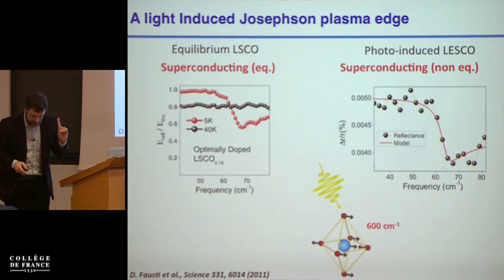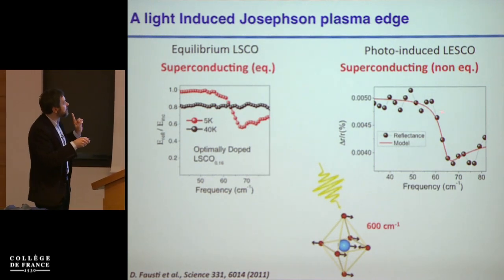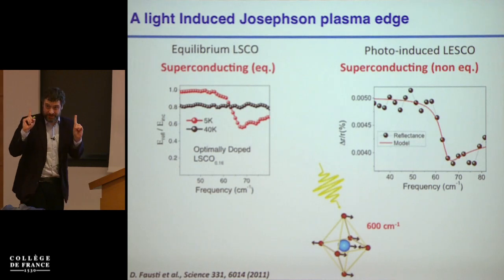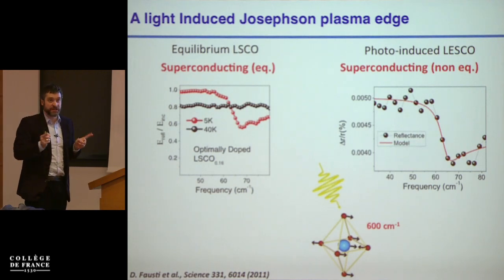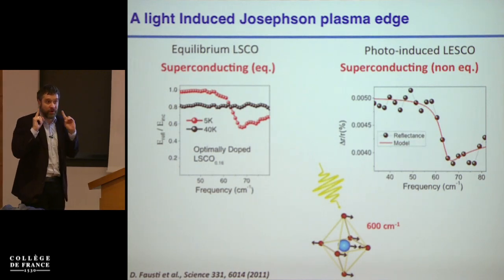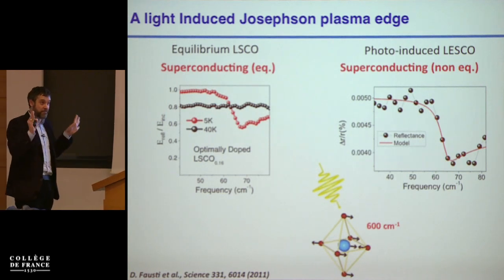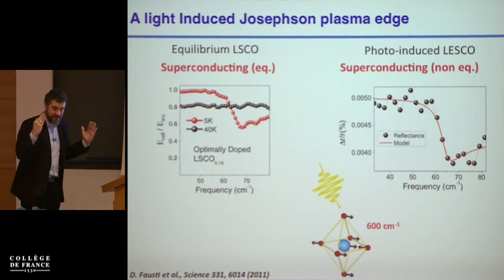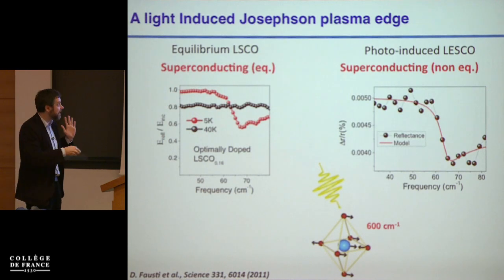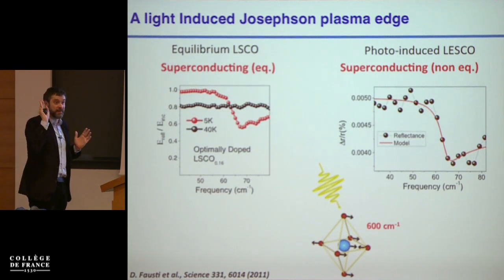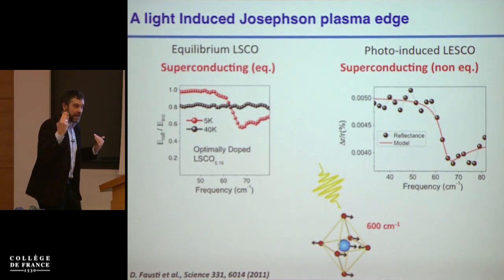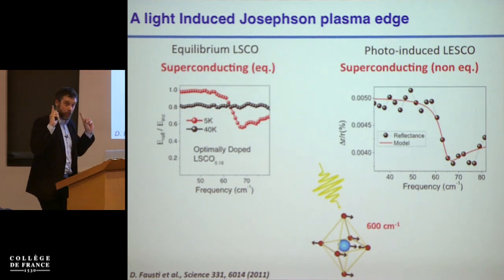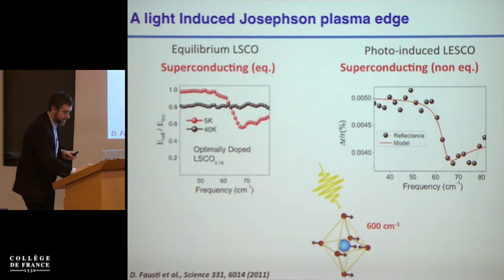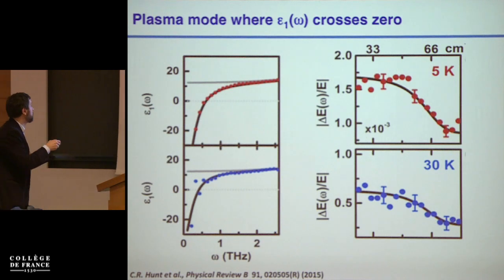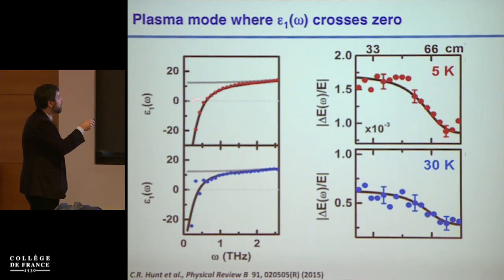And for some people in the audience, the appearance of a new mode that was not there before is also indicative of breaking of one particular symmetry, because the number of modes has gone up by 1. Although I don't know which symmetry I'm breaking, because there's a new zero crossing of epsilon 1, it means that I have a lower symmetry than the initial state. This is actually very clearly observed if I plot epsilon 1 in the transient state.